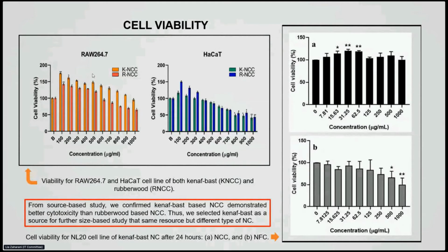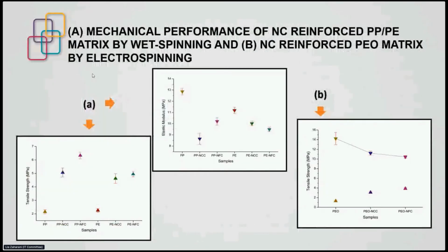From source-based study, kenaf-bast-based nanocrystalline cellulose demonstrated better cytotoxicity than rubber wood-based nanocrystalline cellulose. Thus, we selected kenaf-bast as a source for further size-based study, same resources but different types of nanocellulose. For nanofibrillated cellulose, we are choosing kenaf-bast-based raw biomass for synthesis processing. Mechanical performance of nanocellulose reinforced polypropylene and polyethylene matrix by wet spinning, and nanocellulose reinforced PEO matrix by electrospinning.